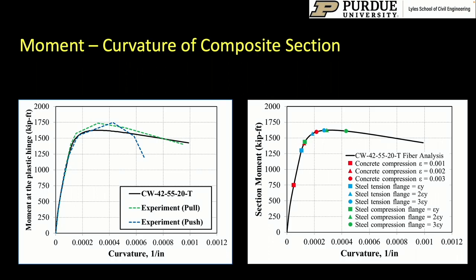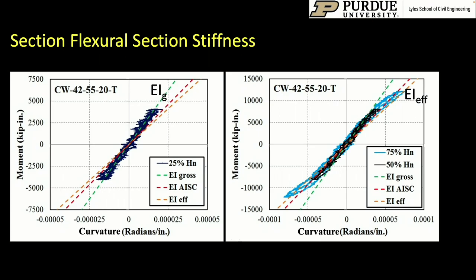In fact, we could take that section fiber analysis and identify the occurrence of various limit states. For example, when does the concrete reach a value of strain equal to 0.003? When does the steel reach a value of strain in compression equal to 2 epsilon y? We were able to identify the occurrence of various events. And what we found was that the peak strength was reached when the steel in compression reached a strain of about 2 times the yield strain. We were able to learn this from the experimental data.